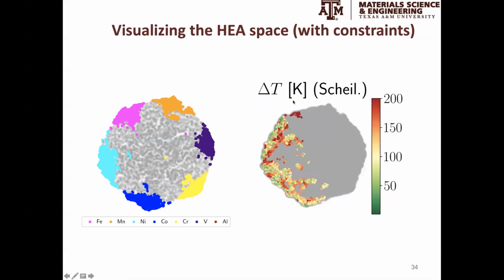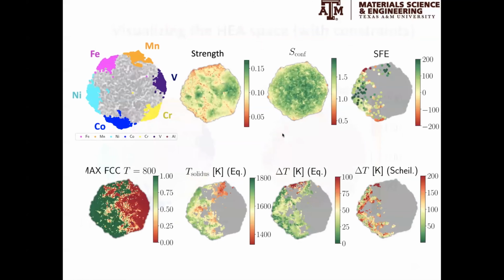If, instead of doing an equilibrium solidification, we actually do a Scheil simulation — taking into account infinite diffusivity in the liquid and zero diffusivity in the solid — and look at the more realistic precipitation sequence, we see that the solidification range actually expands. But there are still some regions in the space where the solidification range tends to be acceptable, and again these regions tend to be closer and closer to the edges in this two-dimensional projection.